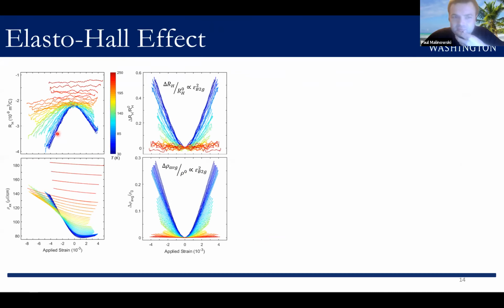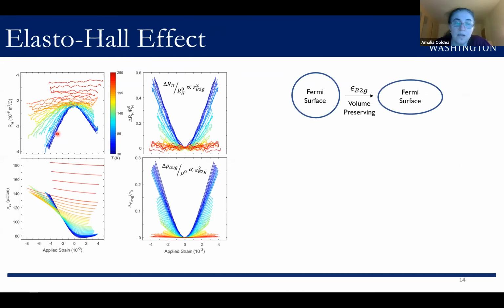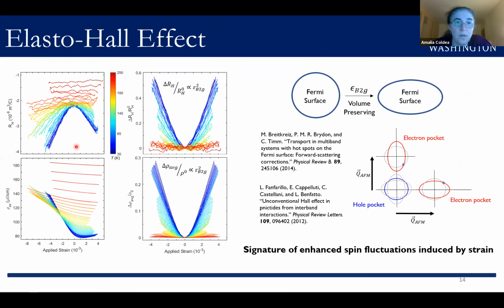Okay, and about the Hall effect, can you extract something about your carrier density by doing a multi-band analysis of your data and see what happens under strain with the carriers and mobilities? So yeah, we can in principle do that. Although if these theoretical works are correct, which it seems like our data is consistent with, then the Hall coefficient is not simply interpretable in terms of a multi-band situation. These results that they derive actually represent a failure of the Boltzmann transport. It's beyond the simple multi-band formula, because if you just look at the numbers,